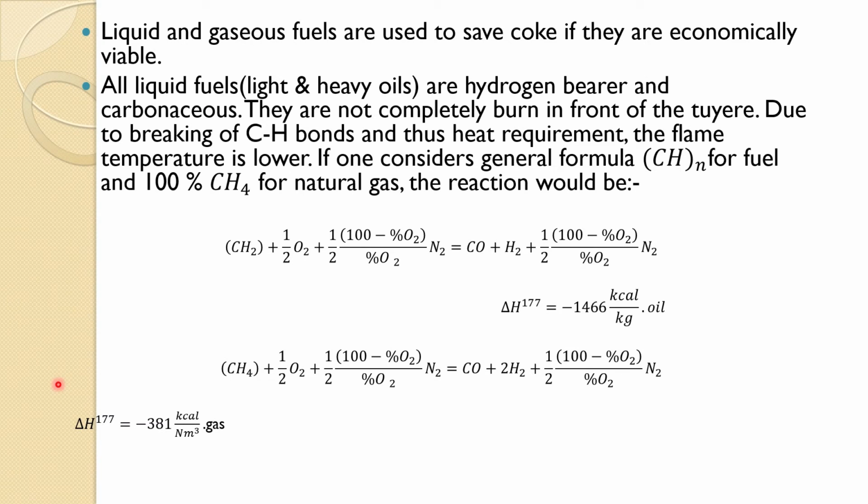All liquid fuels, light and heavy, are hydrogen bearers and carbonaceous, and have carbon and hydrogen bonds. To break them you need heat, and due to that they are not completely burnt in front of the tuyere, in the time which they have. So, the flame temperature is always lower when we use liquid fuel.